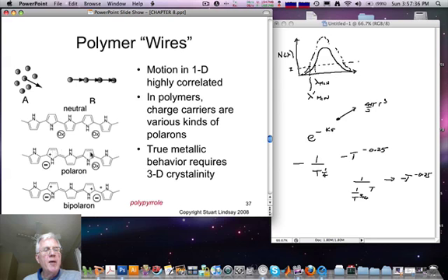This structure, however, is mobile in the sense that because this chain repeats infinitely, the delta G for moving from one site to the next is zero, and so providing there is enough thermal energy to pay the reorganization price of moving from one site to the next, this can be a hopping conductor of positive charge.